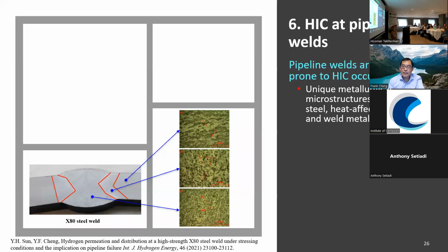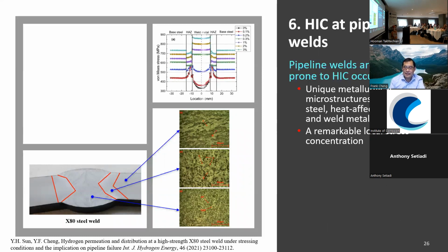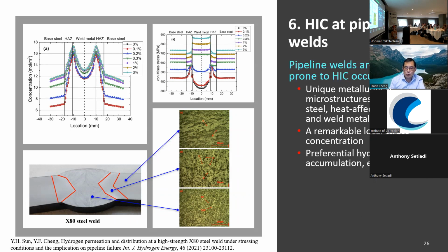Okay, when we talk about hydrogen embrittlement or hydrogen-induced cracking, we realize the pipeline is a welded infrastructure. So the welding area is always sensitive to hydrogen-induced cracking because it has a unique metallurgical microstructure, and it also has local stress concentration, as shown in the simulated results here. Consequently, hydrogen atoms tend to accumulate in the welding area, such as the heat-affected zone.